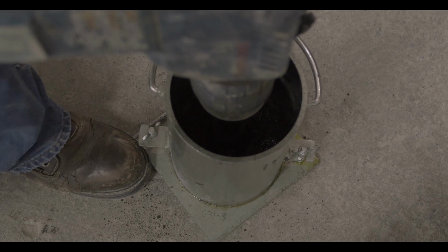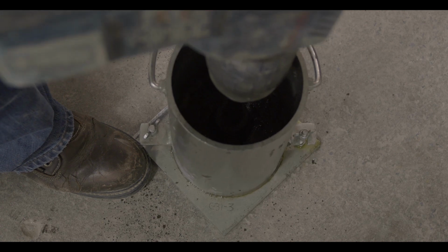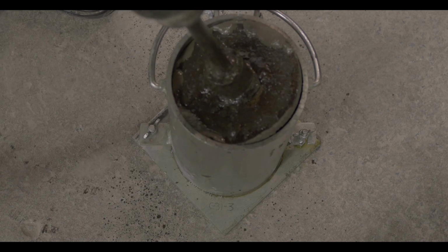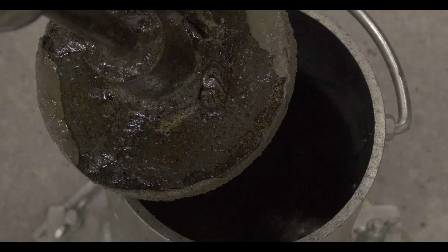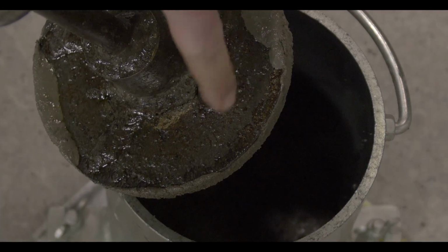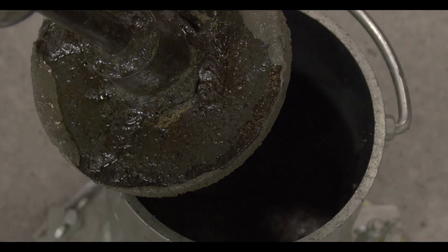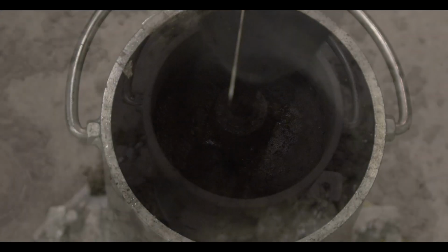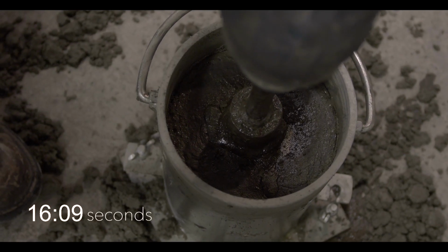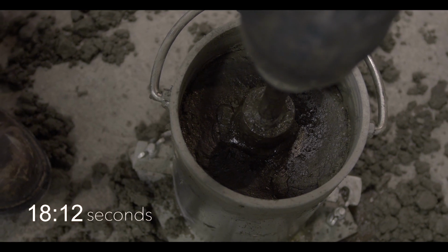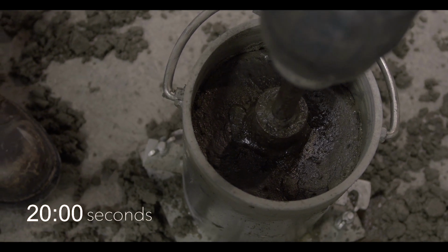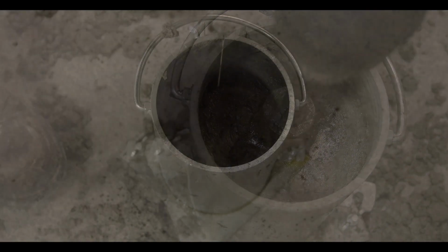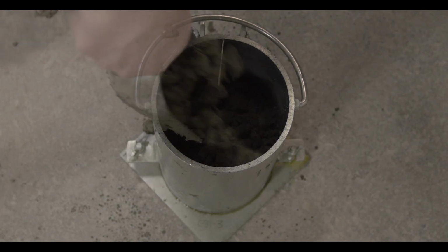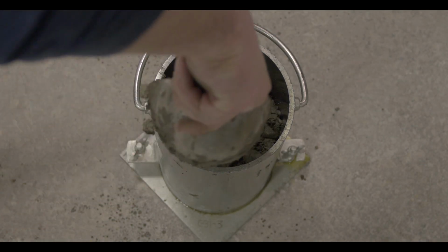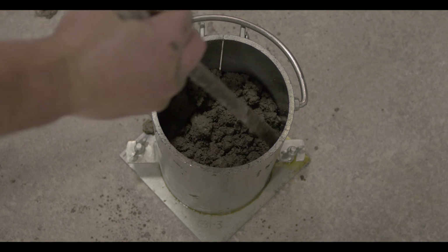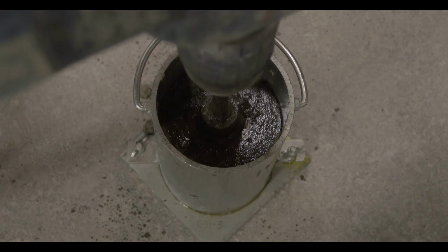As the concrete consolidates, mortar should fill the annular space between the outer edge of the tamping plate and the inside mold wall. Observe the tamping plate. When the mortar ring forms completely around the tamping plate, stop the vibrating hammer. If a significant portion of the mortar ring does not form after 20 seconds, the vibrating hammer shall be stopped and the next layer of concrete added. Repeat the procedure for the second and third lifts of concrete, filling the mold to approximately 1/2 and 3/4 of its volume, respectively.